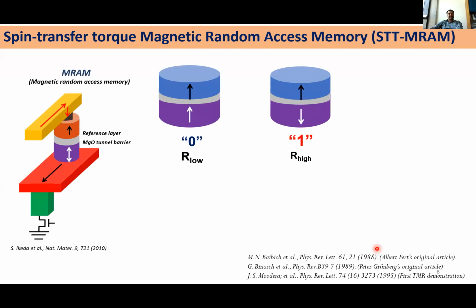Of course, I'm not the one who is starting to do this. We already have spin transfer torque magnetic random access memory, as Professor Subhankar has already given the basics of it. Basically, it is two ferromagnetic layers separated by a non-magnetic tunnel barrier, that is MgO. So you have a reference layer and a free layer. By applying current through this, we can switch the magnetization by injecting the spin polarized current from the reference layer into the free layer. And if you change the current direction, the reflected spins with opposite polarity can switch the magnetization of the free layer.